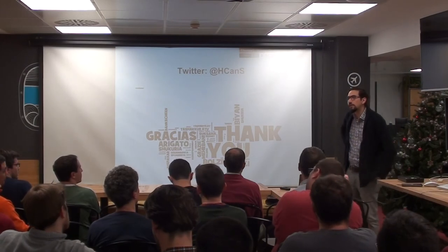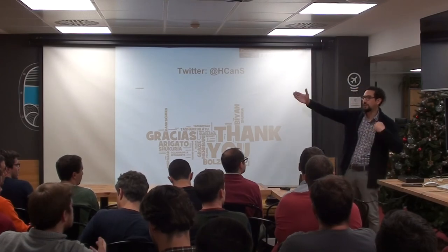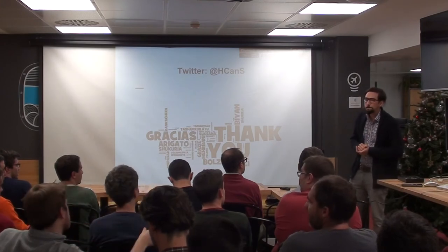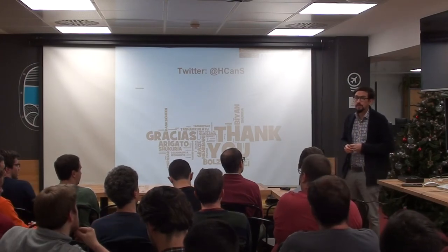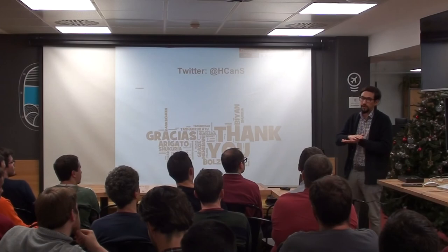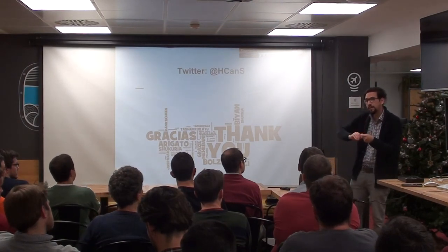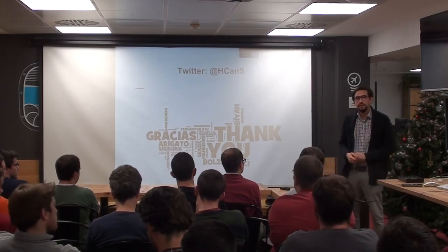Yes, it works only for some materials. For example, materials like aluminum don't have a very wide range. But with nickel superalloys, we can control the hardness. Can you then say one part from the same block is harder than the other? Yes, we can do that. Actually, the technology at the beginning was used for surface modification. So you can have a bulk material of some alloy, and on the top the same material, but very, very, very hard. So it's for wear resistance and other applications. Another question?